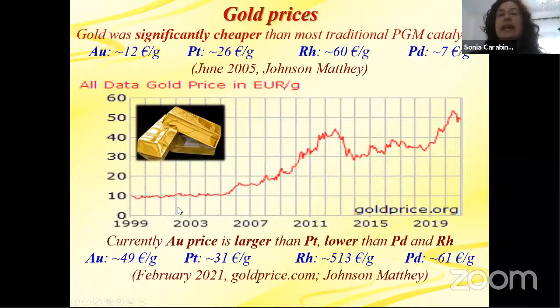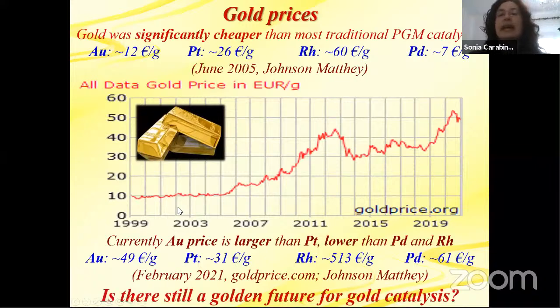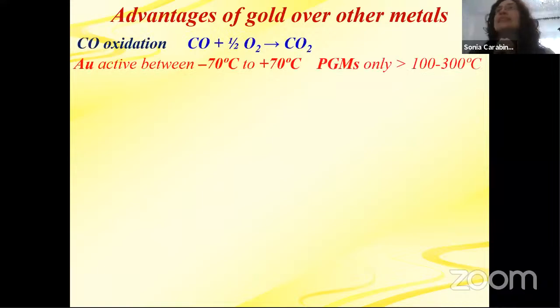So we can ask, is there still a golden future for gold catalysts? So I think there is, especially for these reasons. Gold has advantages over other catalysts, for CO oxidation, which is the most common reaction studied in gold catalysts. Gold is already active between minus 70 degrees and plus 70 degrees, which means that you can do CO oxidation at room temperature in the North Pole or in very cold areas without needing to heat, while the platinum group metals are only active above 100 to 300 degrees.